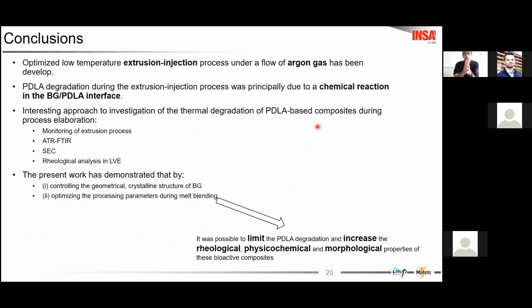So the elaboration at low temperature and the use of inert atmosphere allows us to decrease the degradation of PLA. This degradation was mainly due to the chemical reaction between bioglass and PLA.